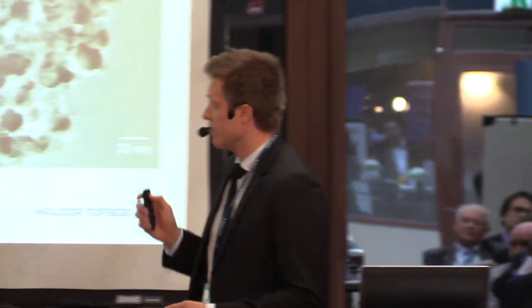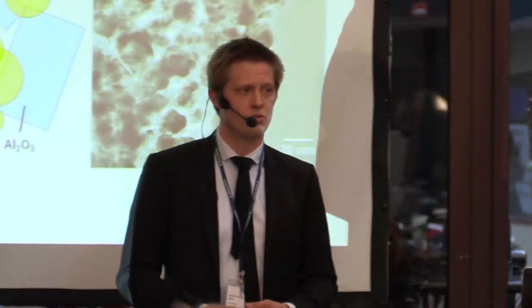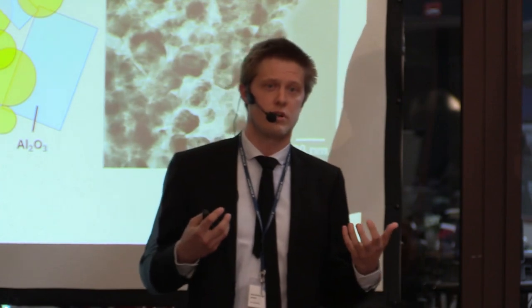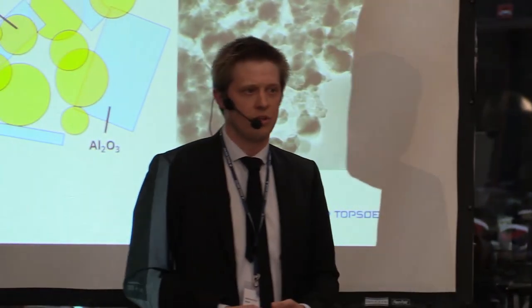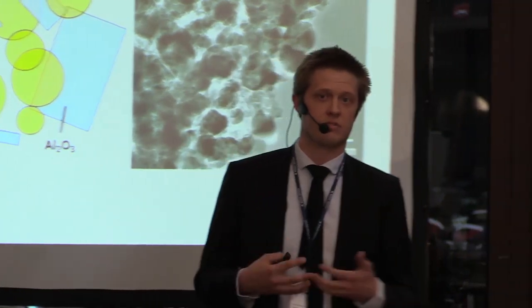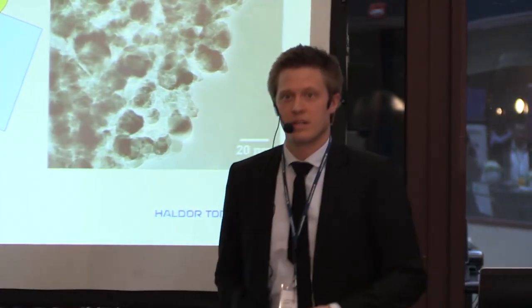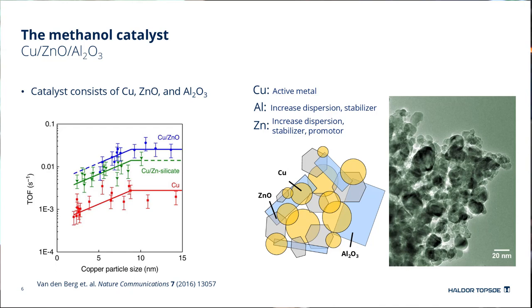Then you add the alumina to the system in order to increase the dispersion of your copper particles. So enhance the area, so you have a large area to do the chemistry. But alumina is also acting as a stabilizer during operations, so it's preventing the crystals from sintering, so you will maintain this high area. And then you add the zinc oxide.